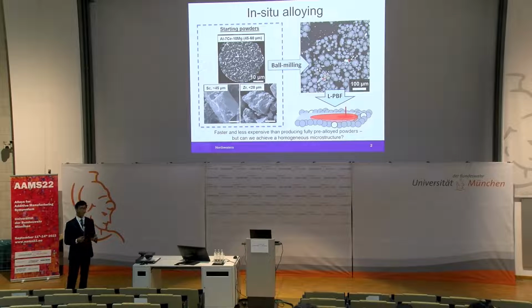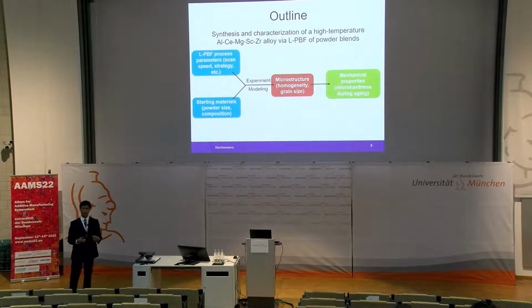Now, the main benefit of this process is that it's considerably faster and less expensive than atomizing fully pre-alloyed powders. But the key challenge is to achieve a homogeneous microstructure. So that will be the focus of this talk. We're going to study the effect of the laser powder bed fusion process parameters and the starting materials on the homogeneity of the microstructure, and we do this through a combination of experiment and modeling. I'll then talk about the effects of this microstructural homogeneity on some other things like the grain size and mechanical properties, specifically the microhardness during aging.